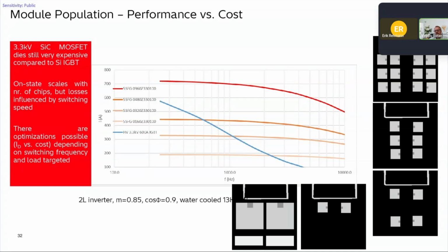What are the advantages when you increase the switching frequency, depending on the application, and so forth. So right now we have in commercial application a module that looks more like this. So half populated would be this current output line that the customer is switching at 10 plus kilohertz. So they switch in a DC-DC application at very high switching frequency at 3.3, of course, to reduce the inductor. And this would simply not be possible with silicon. So the current output at 10 kilohertz for a silicon module is close to nothing. So that's very, very small.